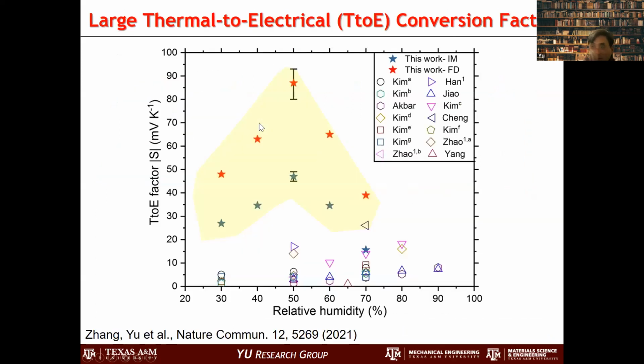Because of the time limitation, I'm not going to go into too much detail, but we're just showing you the thermal to electrical voltage conversion factor, which is equivalent to S, the thermal power. Previously what I showed was 10 millivolt per Kelvin. Now it becomes 90. It's actually one order of magnitude higher. It's really large. Then we need only a few devices to make a device out of that, and it becomes fantastic. That's what we have done.